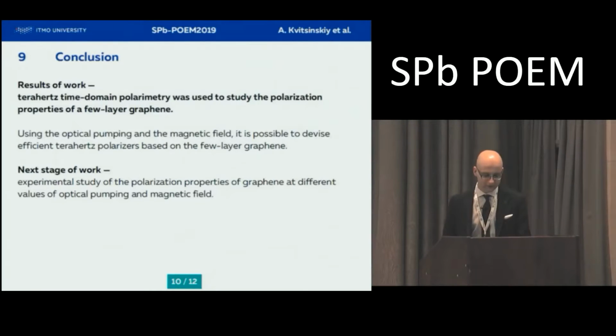As a result of this work, frequency dependencies of azimuth and ellipticity angles of the polarization ellipse, and the polarization ellipse of the few-layer graphene on the silicon substrate and a sample of the silicon substrate, were obtained experimentally using terahertz time domain polarimetry. The results show that it is possible to devise efficient terahertz polarizers based on few-layer graphene.